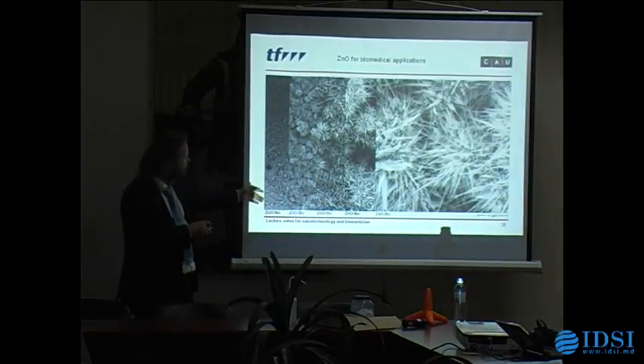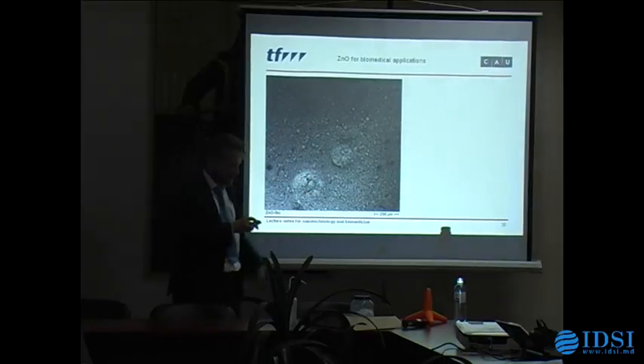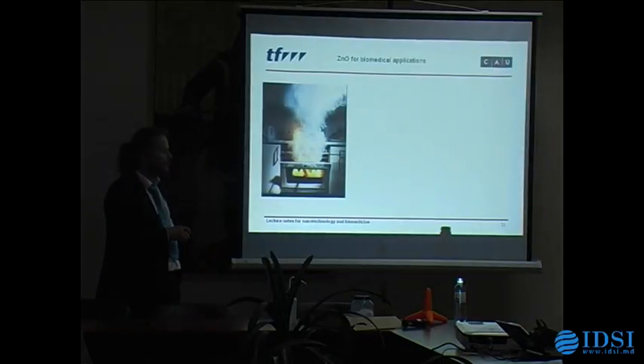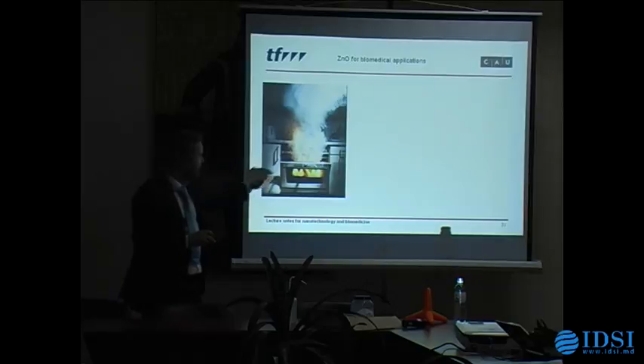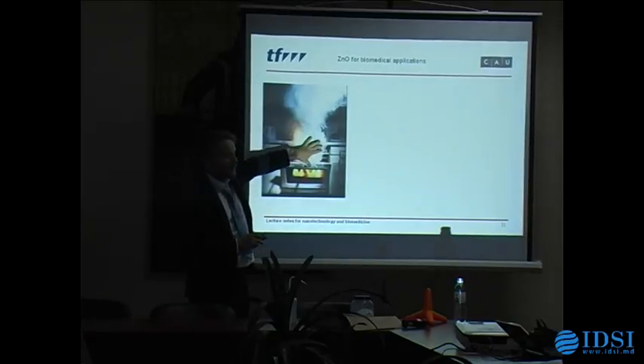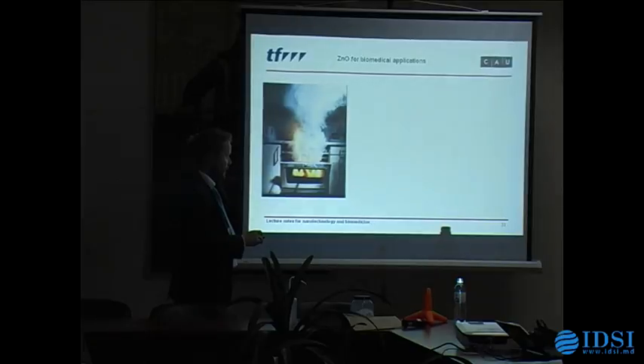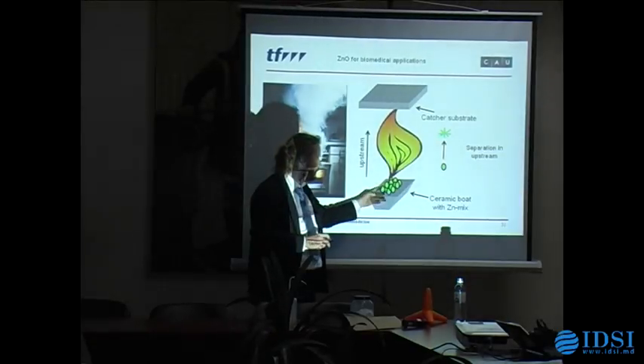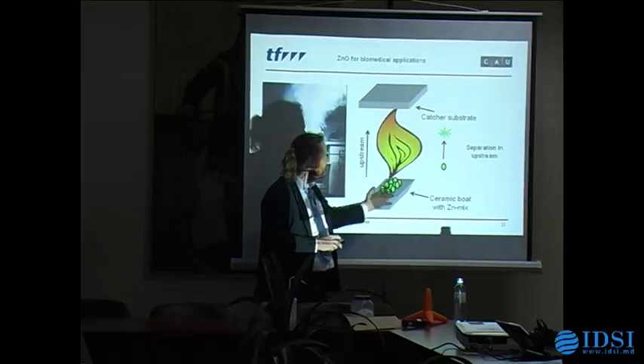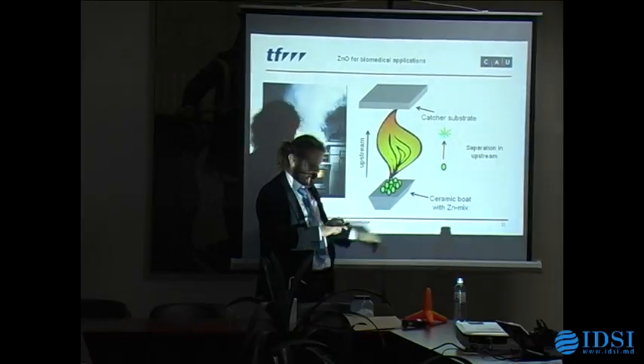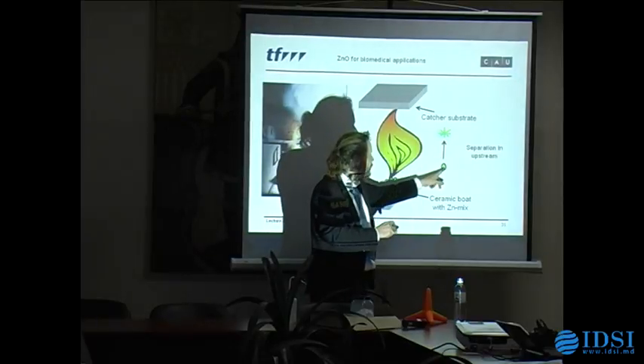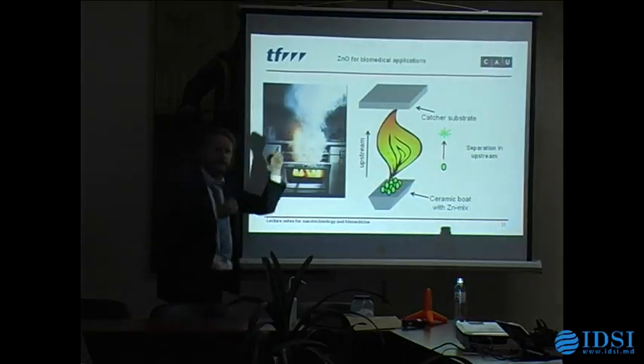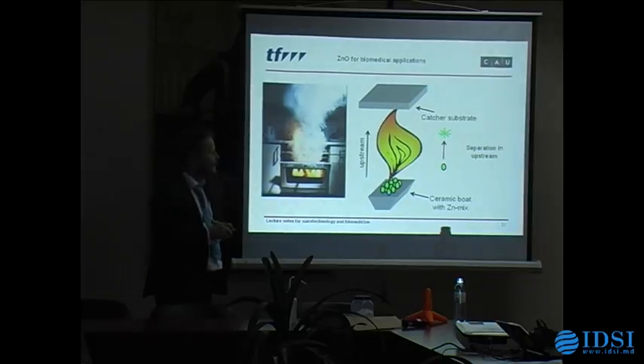But this was a problem because this was only useful as surface coating. So we went one step further and we observed the same accident like you have seen if your pizza is too long in the oven and you're opening it, exposing it to oxygen, it will be immediately oxidized. And then some vapor is coming up, and this is containing particles. You can do the same with your oven. You have your zinc particles, and now we call this flame transport synthesis because you're using this flame, the stream up, where freely now the zinc can be oxidized, and it can grow in all crystal directions like it wants, and it can be done in a very fast manner.